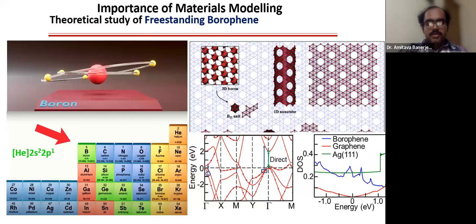Now if you see this band structure in the first Brillouin zone, interestingly, along the gamma to X direction, an energy band crosses the Fermi level, indicating the metallic properties of Borophene. However, along the gamma to Y direction, there is a direct band gap of around 2 eV. This is the band structure of a particular phase of Borophene. As a result, the Borophene monolayer is highly anisotropic, which we have already discussed, as Dr. Negi and Dr. Pranay said several times, that Borophene could show anisotropic properties.